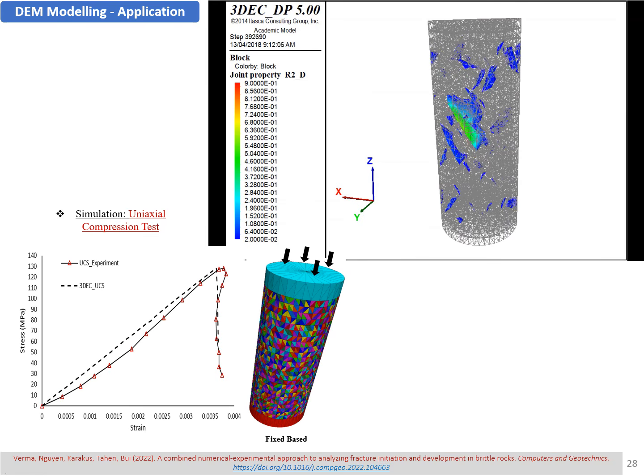The result of the uniaxial compression strength simulation is shown in this given slide, which shows a really good correlation of the numerical output with the experimental observation. Now, these correlations were found to be good not only at the sample scale but also at the local scale damage process, the details of which can be seen in the publication shown below in the slide.